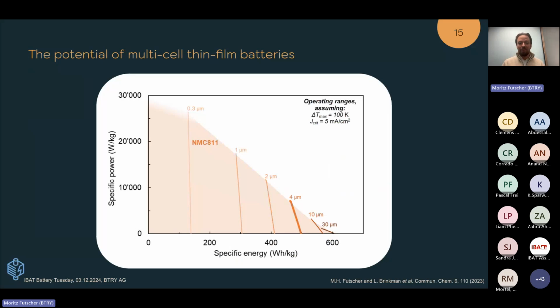So now what is the potential of such stacked thin film batteries? We also did a model. This is a thermoelectric model where we calculated what the limits of this cell design are, how thick the cathode needs to be, and what specific energies and specific powers can potentially be reached. Here we use NMC 811 as a cathode material, and we assume that 10 of these thin film cells are stacked on top of each other. In addition, we assume a critical current density of 5 milliamps per square centimeter for the solid-state electrolyte, and a maximum heat generation of a temperature difference of 100 Kelvin. And this basically defines this area here.